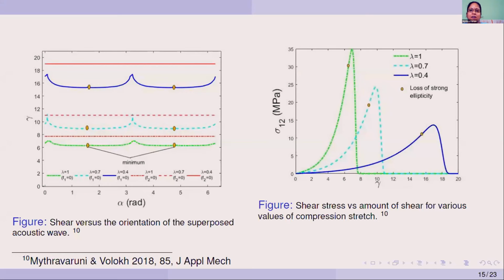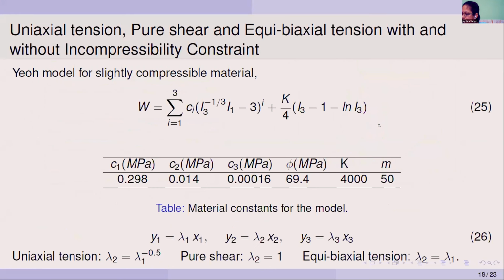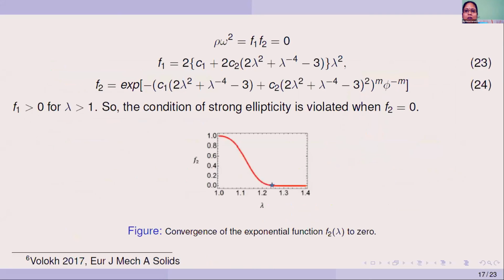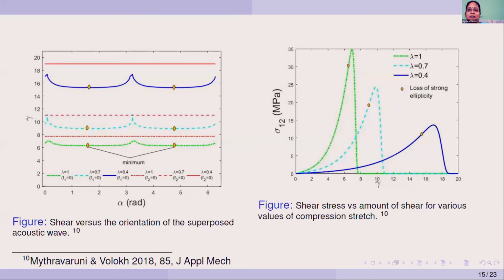And this figure on the right shows the shear stress versus shear strain curve for different compressive stretch values, and these limit points show the loss of strong ellipticity. And we can see that with an increase in compression, the onset of damage is delayed.